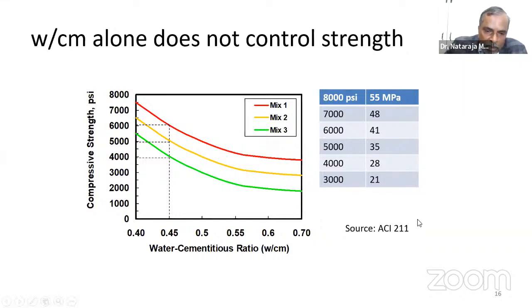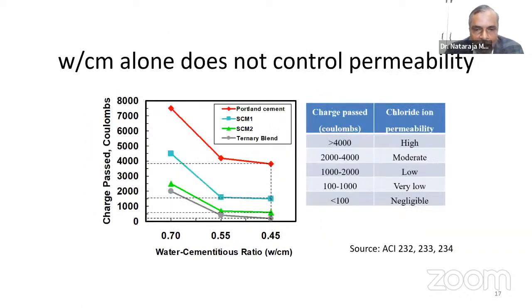So when the water becomes more and more, where the water cement ratio exceeds 0.5, going up to 0.7, our concrete is definitely vulnerable. But with the combination of supplementary materials, your concrete will be substantially better in terms of strength. But if you see in the next slide, kindly see, the moment you start using the supplementary cementing materials,